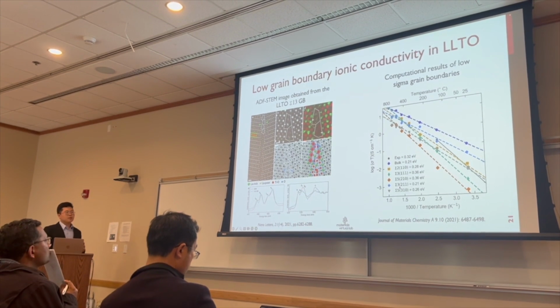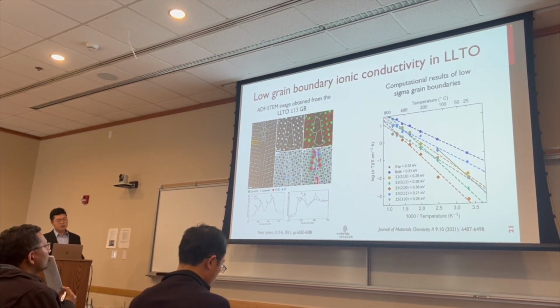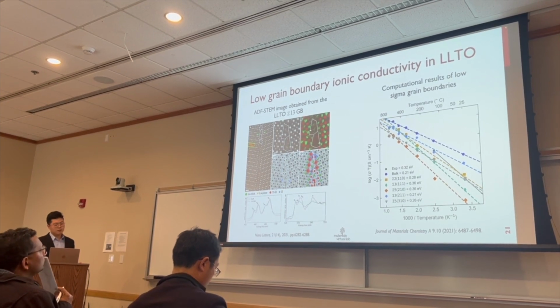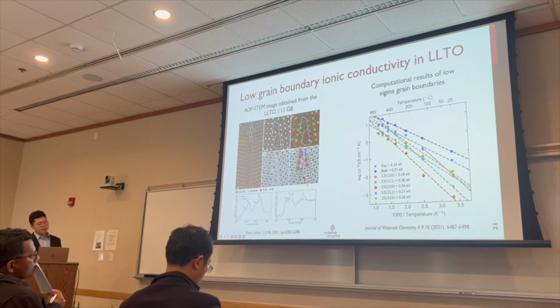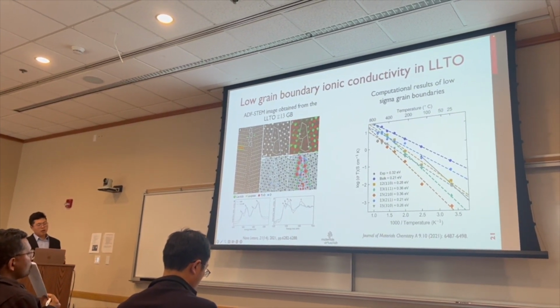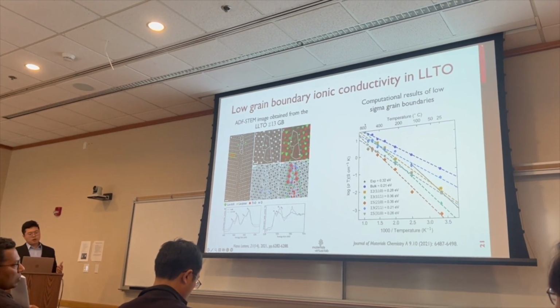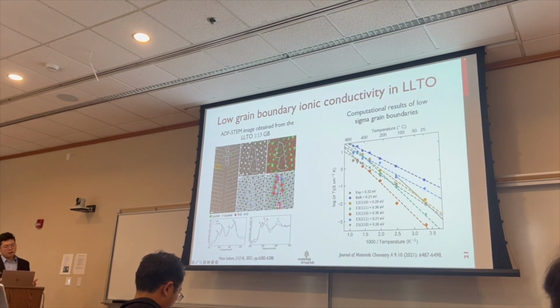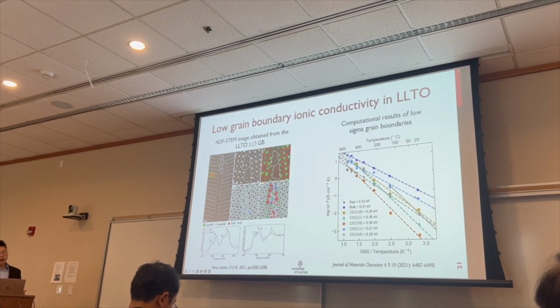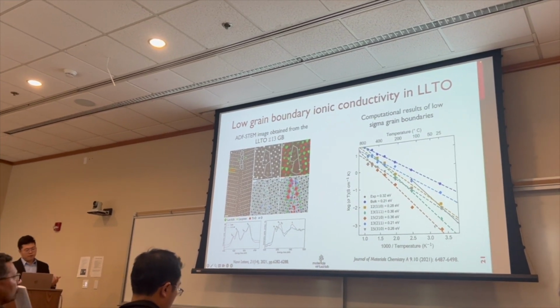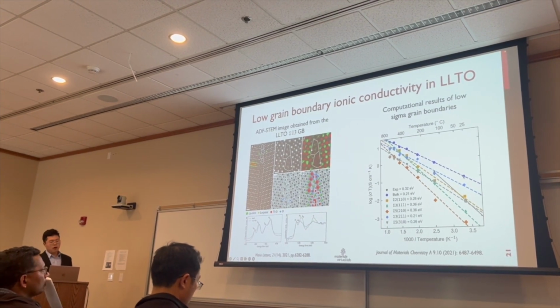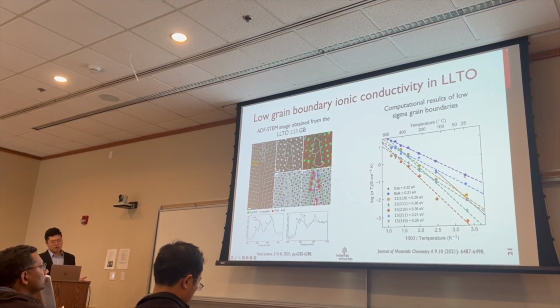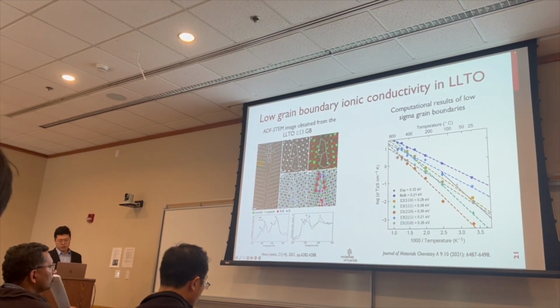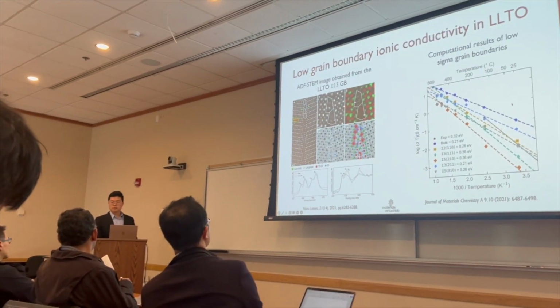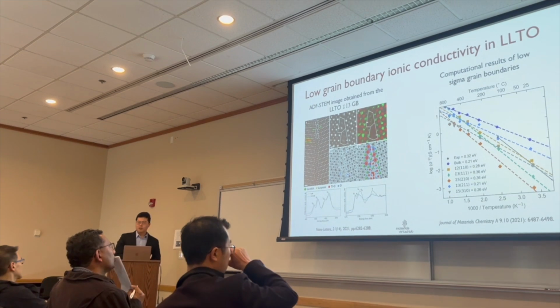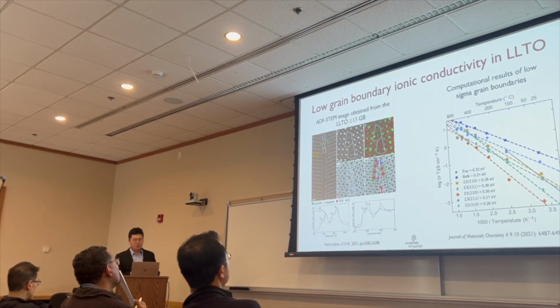For LLTO, there has been extensive experimental and simulation work to explain the high grain boundary resistance. From experiments, we know that there is formation of titanium oxide and also lithium depletion at the grain boundary region. From computational results, we also see that for different low sigma grain boundaries, the diffusivity values are at least one order of magnitude, or a few orders of magnitude, lower compared to the ionic conductivity in bulk, and the activation energy is also higher in the grain boundary region. Is this simulation AIMD or classical potential? Classical, yeah. That's the only thing we can find.